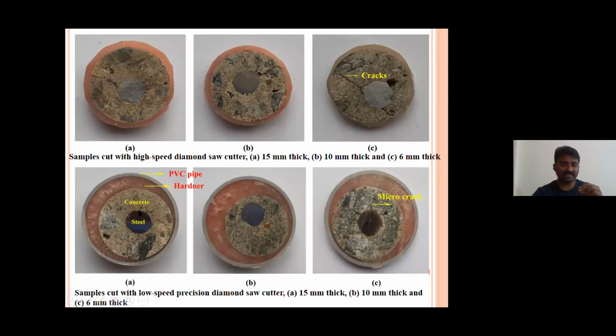For 15 mm thick samples, the damage is very less. For 10, there is some amount of damage, and for 6, because of a little bit of heat, we could observe some micro cracks at the interface. So from this study, we concluded that we should have at least 15 mm thick samples, and we should use a slow speed diamond saw cutter for cutting the samples.